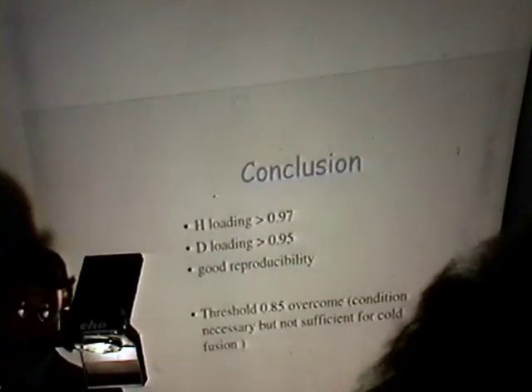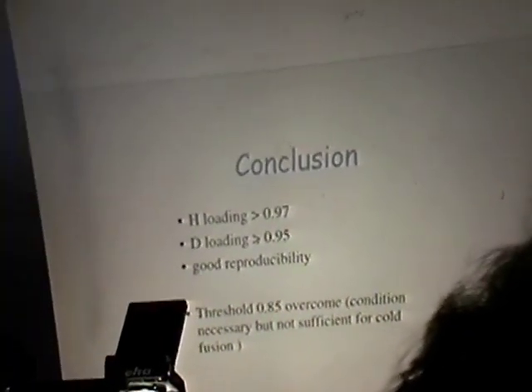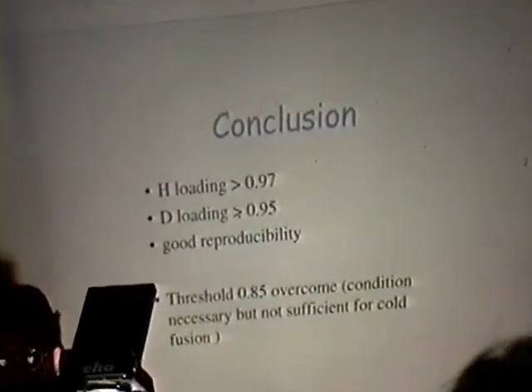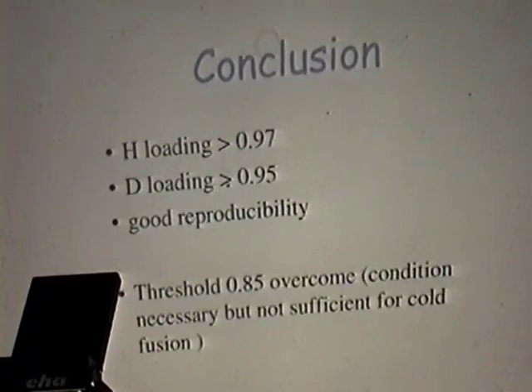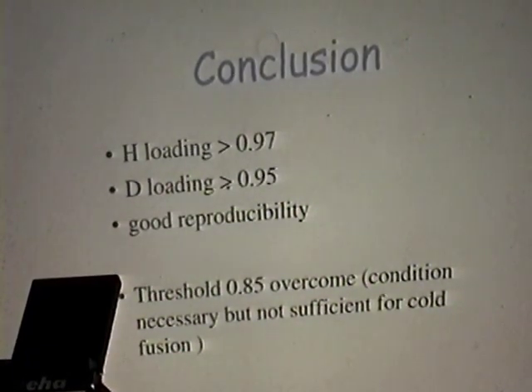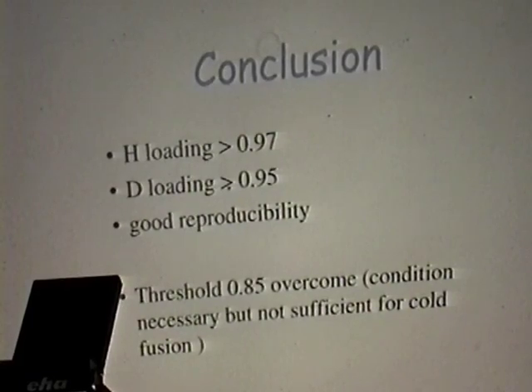In my conclusion, I indicate only the possibility to reach very high loading with the method developed in Frascati, indicated as a limit 0.97, and very high loading, but more difficult for deuterium loading, above 0.95. It is important to stress that this is over the limit of 0.85 that is a necessary condition for fusion. For the future, I hope to develop a more precise calorimeter in order to reproduce the challenging result presented here by Professor Miley, Antonio Adelino, and Francesco Scaramuzzi. Thank you very much.